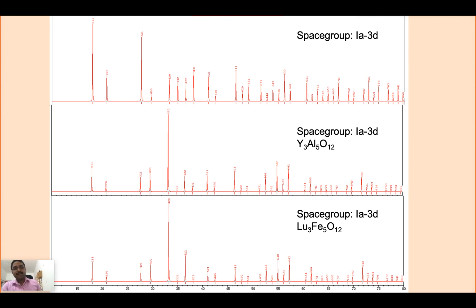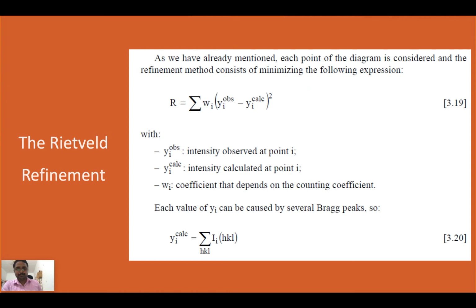So with the ABC values I can produce the entire spectrum. Then comes the Rietveld method. The Rietveld method is a different aspect, where earlier they had used only ABC values. Now we are going to use integrated intensity values, because it is dependent on the scattering factor of the atoms. So when you have to include every aspect of your sample, then you will go for Rietveld refinement. Rietveld refinement is nothing but minimizing the difference between your calculated pattern and observed pattern.